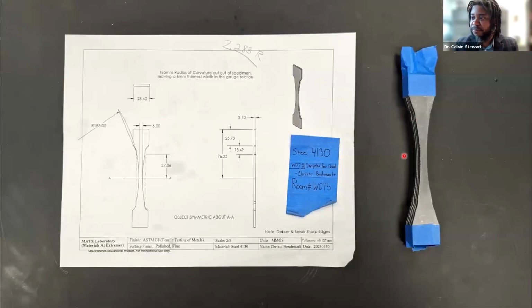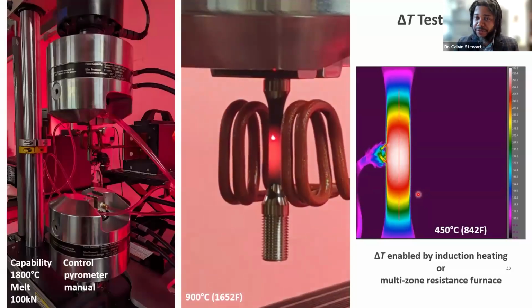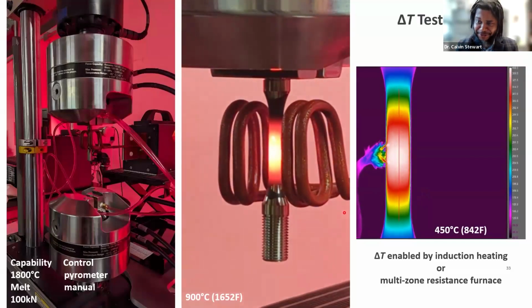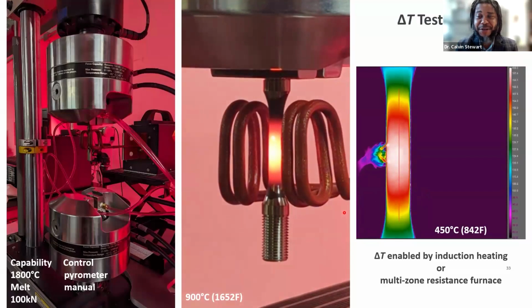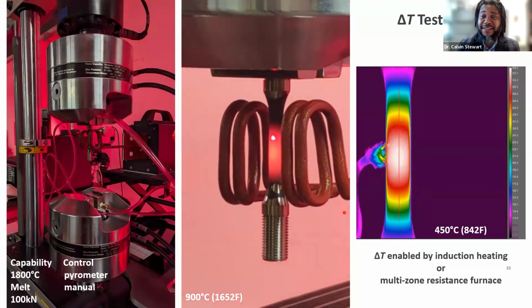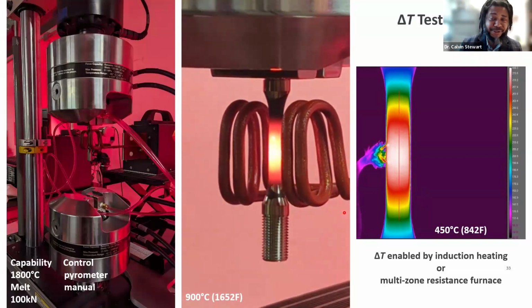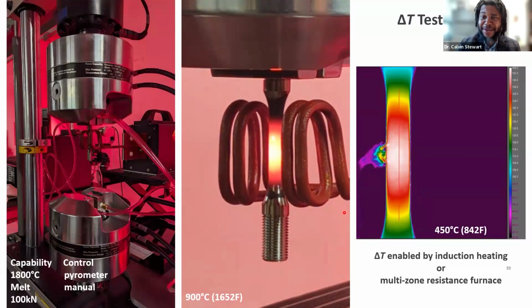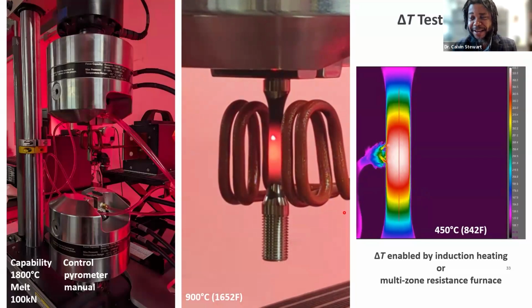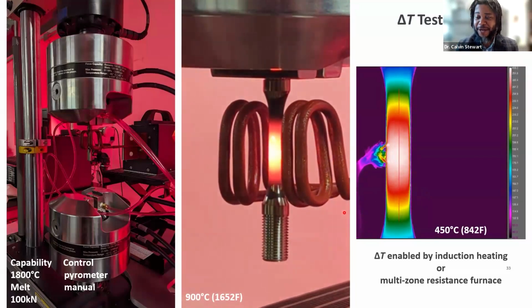And we've machined some 4130 steel samples with a specially designed gradient for us to test and assess this technique. Or whether it's the Delta T test setup that we spent a lot of money building, but with very cool capabilities of testing with control to 1,800 degrees Celsius. If we're not careful, any metal we put in here, or just about any metal we put in here, is going to melt. If we're not careful with control, right?